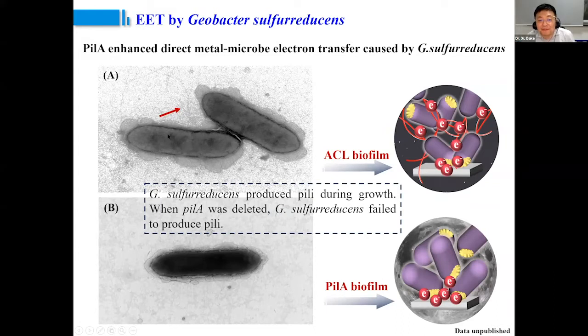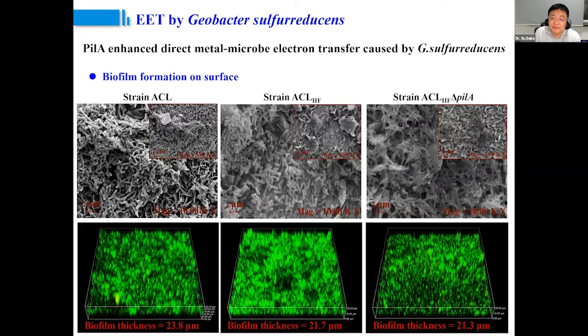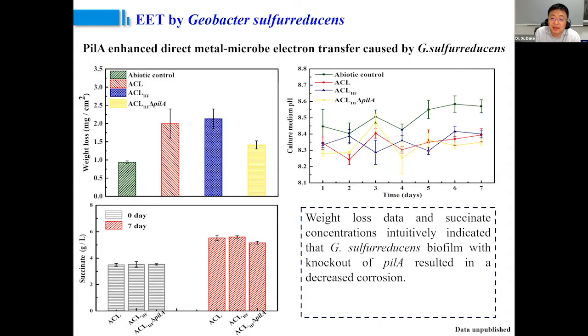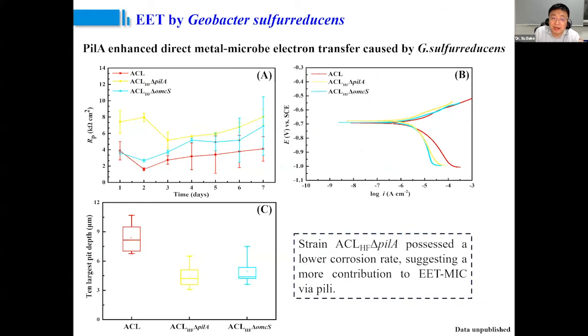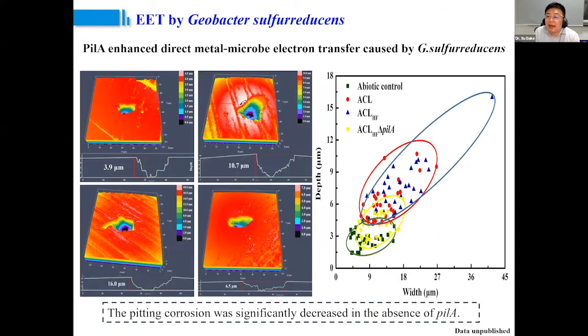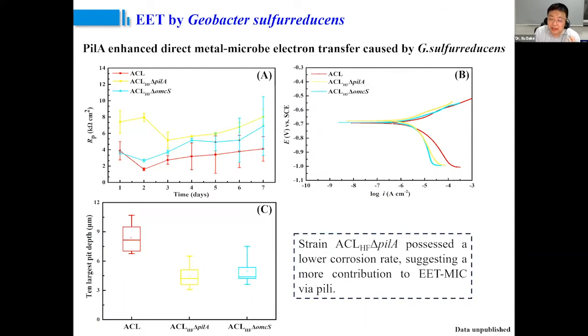We do a TEM image. We found that for the wild type, we can clearly see the pili. But when we knock out the pili genes, the Geobacter cells lose their pili production ability. We do similar electrochemical measurements, weight loss, and pitting morphology examination. We got one conclusion: pili are involved in MIC by Geobacter electron transfer. Then we compare which is more important, OMCs or pili. Based on the current data, they are similar contributors to MIC caused by Geobacter sulfurreducens.